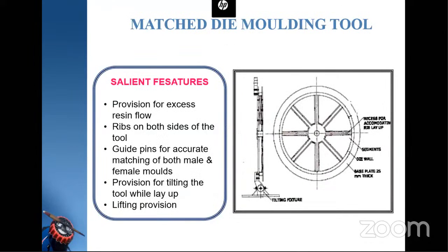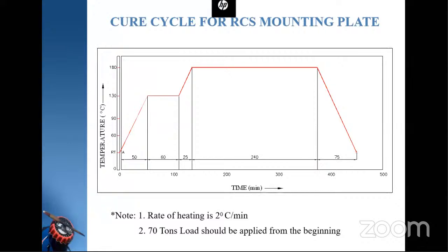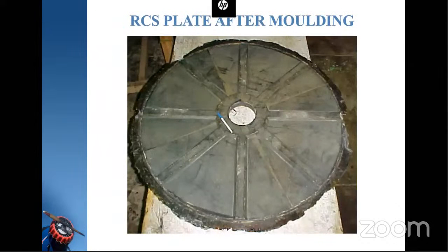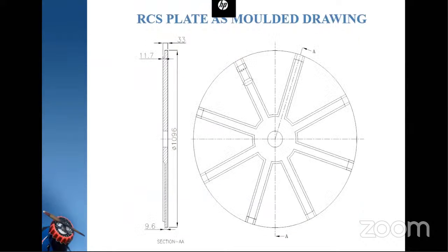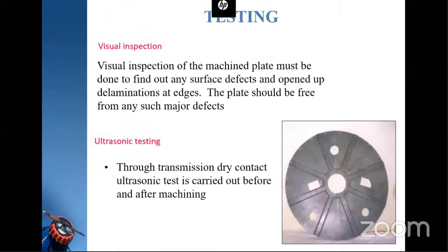This is the plate which has extra stiffeners on both sides. So this is the cure cycle which we have used. This is the plate photograph which we have developed, which is having 8 ribs on both sides, of similar shape. So here you can see the thickness cross section of the component. Here you can see the plate is tested ultrasonically and found in good condition.